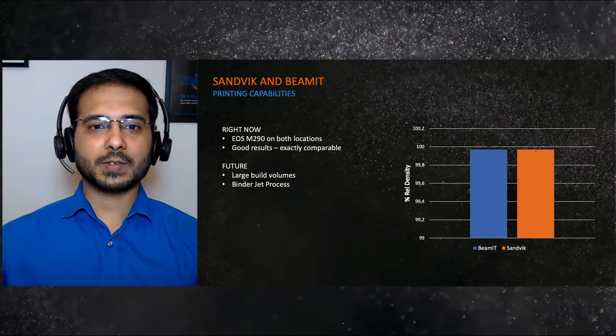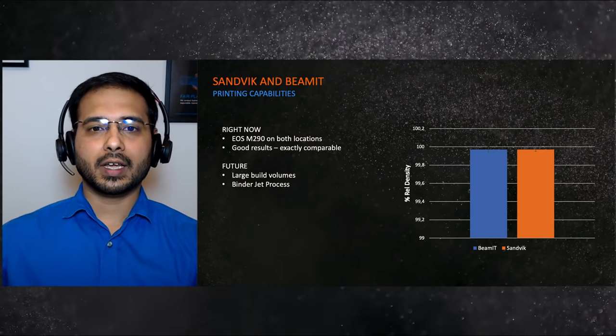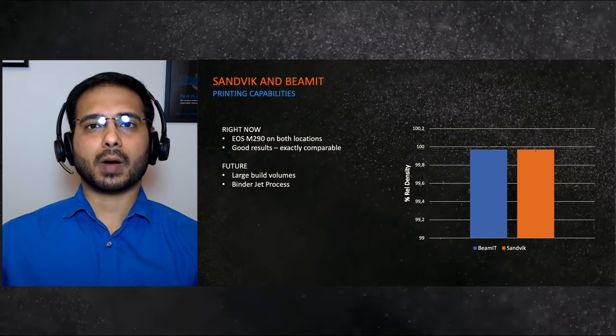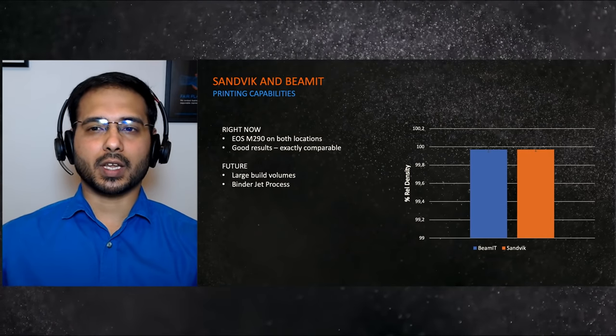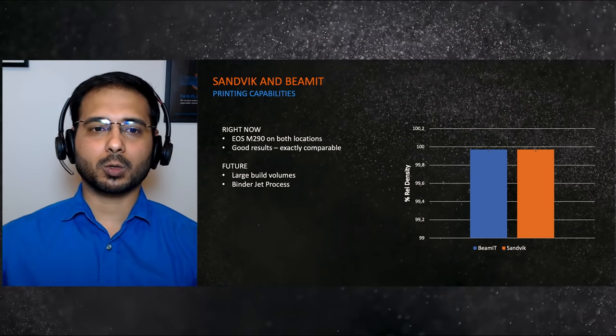Yes, of course. This transfer of parameters was not the only step; we also ensured the build process qualification protocol, including post-processing and quality systems as well. In both cases, in terms of part relative densities, we observed 99.97% plus mean values with very minimum standard deviation all over the build plate. The microstructures were also studied and found to have identical results with 50-50% of ferrite and austenite phase in the material. Apart from this, various properties like hardness, tensile, and impact have also been studied and compared, and they were found to be equivalent at both sites.